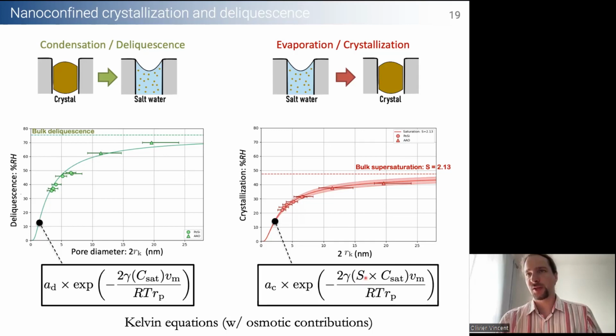And the supersaturation, for NaCl solutions, the maximum supersaturations that have been measured by levitating water droplets very carefully and drying them slowly is around 2.2, and we reach supersaturations in our system that are very similar to the maximum supersaturations that we can measure very carefully for NaCl in control systems.